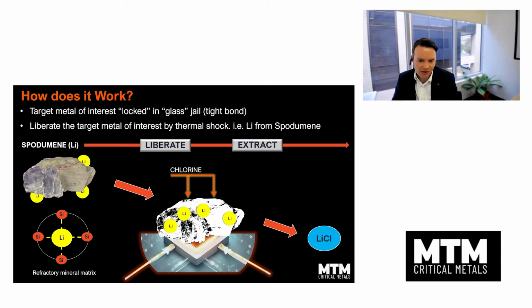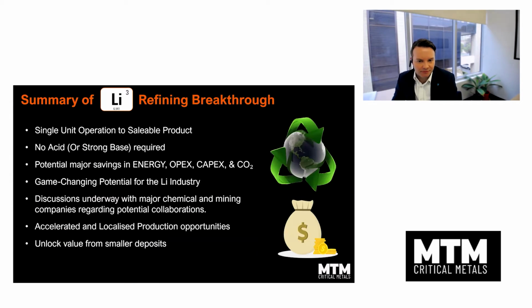And the novelty of the flash technology is that the rapid heating, so going from ambient to over 1000 degrees in milliseconds, seems to break that glass and break that silica lithium bond, and therefore liberating the lithium. And therefore, when you add chlorine into the mix, the lithium readily reacts with that chlorine. So you're essentially distilling off the target metal of interest and leaving the unwanted stuff behind in a very elegant and efficient process. Next slide, please.